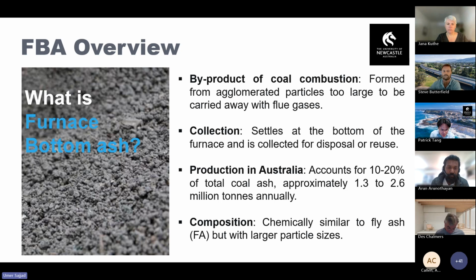In composition, it's chemically similar to fly ash, but with larger particles. So when we compare it with cement and other cementitious products, it's slightly coarser than those cementitious products. That's why we have to do some pre-treatment. Then we can use it as an SCM or as other fine aggregates.